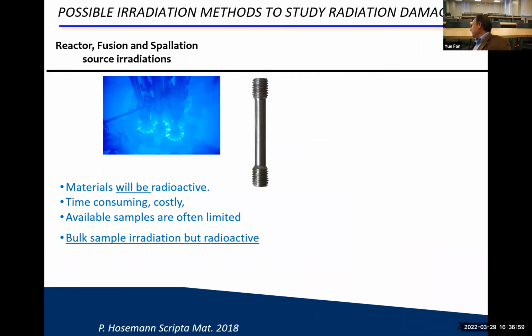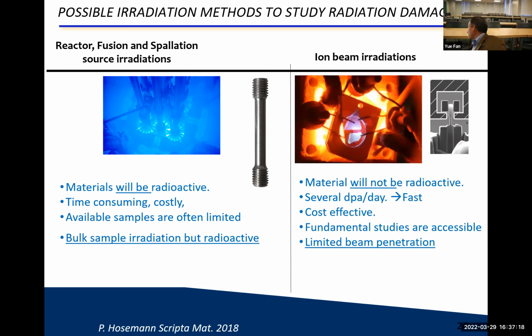Now, when we have our material, we want to irradiate it. Usually we have two ways to do this. We can either have a reactor radiation, which leads to macroscopic dog bone samples and what have you. However, they're going to be highly radioactive, and therefore we would like to do smaller samples to keep it safer. But we also can do ion beam radiations. You have, of course, one of the world's premier ion beam facilities here. I'm well familiar with this. With ion beam radiation, your penetration depth is limited, so you also have to go to small scale mechanical testing, because otherwise you can't test the material in that volume. In either one of those applications, small scale mechanical testing can be useful, and so I'm going to show you examples of small scale mechanical test data of these phenomena we just discussed.